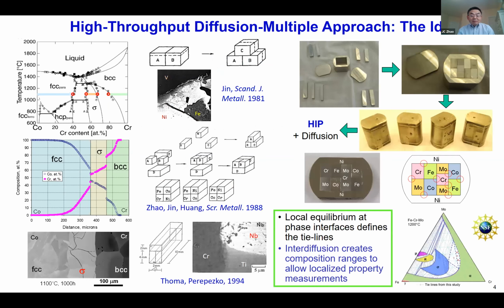So this is what I call the diffusion multiples. So basically, instead of making diffusion couples, this has been used for phase diagram determination and diffusion coefficient extraction for more than a century. And this is a very mature technology. I can see that a lot of the solid state phase diagram tie lines are from this local equilibrium at the interface. You can see the composition jump from here to here. That's how those pairs of tie lines are determined. Right? So this has been used for many years. There's nothing new in there.